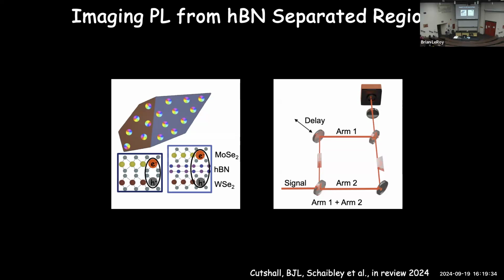And so that's what I'm trying to depict here. I want to have uniform phase here. I have a macroscopic state in this side of the sample. And so the way I'm going to do that is I'm going to actually image the emission of the PL, the photoluminescence from this sample, and I'm going to interfere it with itself. So I'm basically going to bring the emission in here, split it into two arms, and recombine it together.